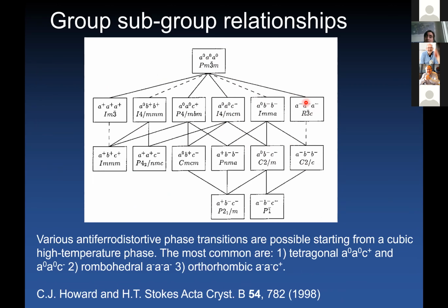So that's typical of systems such as lanthanum aluminate, LSAT and things like that. We have this pattern of rotations, or the orthorhombic systems are very common. We have a Pnma type of symmetry, and a minus, a minus, c plus type of rotations, or orthorhombic systems. So, for example, the case of strontium titanate that is very often studied is an a0 a0 c minus type of distortion, where you have out-of-phase rotations along one axis.